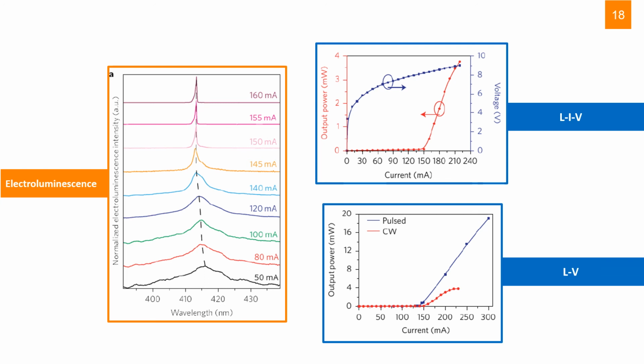They have seen for the light current voltage measurements that this is a pulsed current injection, and this is a continuous current injection. The continuous current injection shows a well-defined stimulated emission kink, and this observation, with a full width at half maximum decrease with increasing current injection, means that the device is lasing or in the lasing operation.